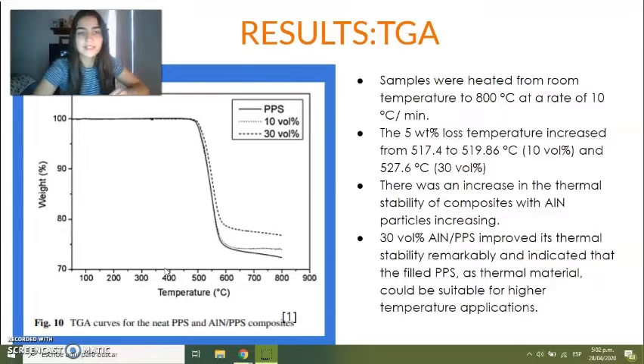Therefore, as we can see, 30% by volume of AlN in PPS improves its thermal stability remarkably, and indicates that the filled PPS as a thermal material could be suitable for higher temperature applications. To conclude, the reasons for the improvement in thermal stability of filled PPS were probably attributed to the increase of physical and chemical cross-linking points and the interactions between the AlN filler and the PPS matrix.